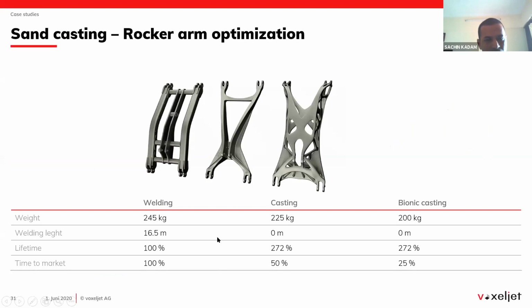If you see the welded parts, weighing 245 kg, the total welding length was 16.5 meter. And if we compare the casted parts, the casting weight was reduced by 20 kg, almost 10%. And the lifetime, the strength, was increased almost 3 times. The middle one was the first iteration, and the last one was the further optimization of the swing arm. After further optimization, the weight of the swing arm got reduced further by 10%, and the lifetime again increased, almost 3 times more than the conventional method.